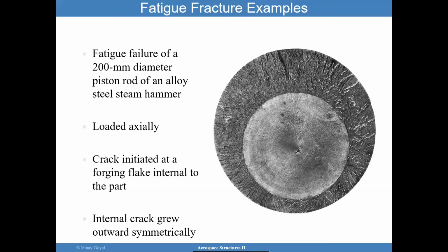Here's a fatigue failure of a 200 millimeter diameter piston rod of an alloy steel steam hammer loaded axially, and the crack initiated at a forging flake internal to the part. So a crack does not always initiate from the external surface, but it can initiate internal to the part. And the internal crack grew outward and symmetrically, as you can see.